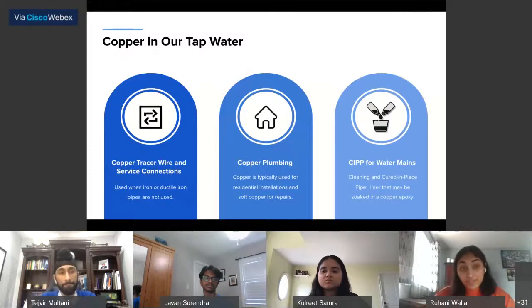So in one specific version of the polymer, copper particles were used to stabilize the formula and create a conductive epoxy. Conductive epoxies, again, more research, are used in cases where the risk of mechanical cracking, such as the pressure of water in pipes, is high. While we can't say for certain, of course, that the CIPP used a copper-based resin, our research suggests that this is a possibility for why Toronto had more copper relative to the other regions.